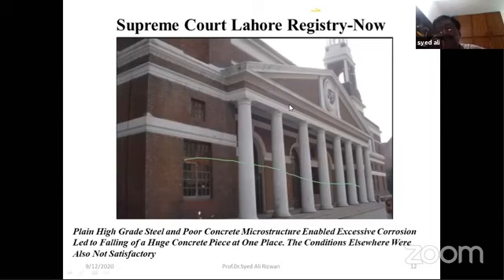So we observed all the requisite steps. We measured crack widths, everything. But there was no appreciable deflection. Some cracks were there. And when we did some laser testing, we could sketch the reinforcement pattern. The reinforcement pattern looked okay. It was, I think, 1 inch or 3/4 of an inch diameter plain steel. So it showed that this building was quite old and deformed steel was not available.